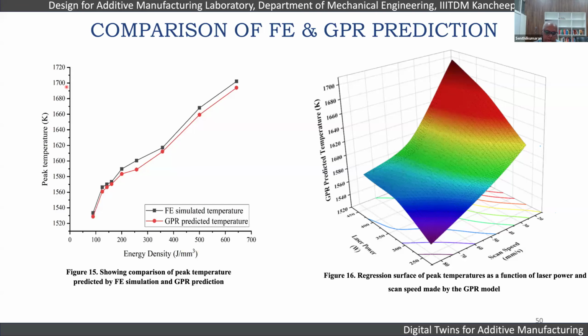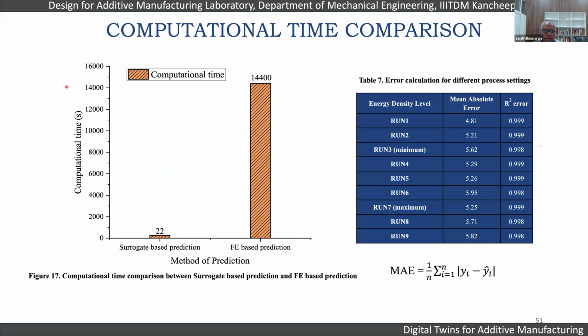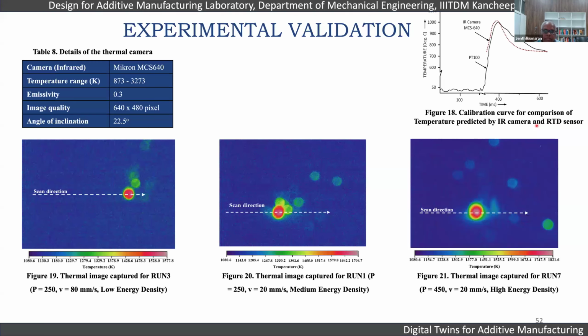So this is the peak temperature that is being obtained. Here you can see that if you use a GPR surrogate-based model prediction, we are able to reduce the computational time from 14,400 seconds to 22 seconds. You can see the drastic reduction by simply doing a one-time simulation and using that repeatedly for any model. So the surrogate models are able to simulate the entire temperature in a very short span of time. And we also calculated the mean absolute error.